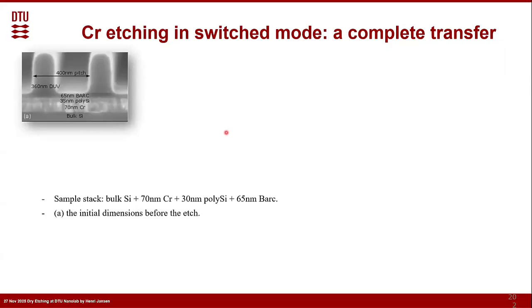But looking at that, now we can have this chromium as a hard mask, where we have the cryo process running not only for etching the chromium hard mask, but also the silicon. That means we can go, let's say, for bulk silicon, we have a layer of chromium we put on top of polysilicon. This one is needed to etch the chromium. I will show it directly. And there's now, for the DUV, what we call a BARC layer. But it is not really essential for this story, and a resist on top for the DUV resist.